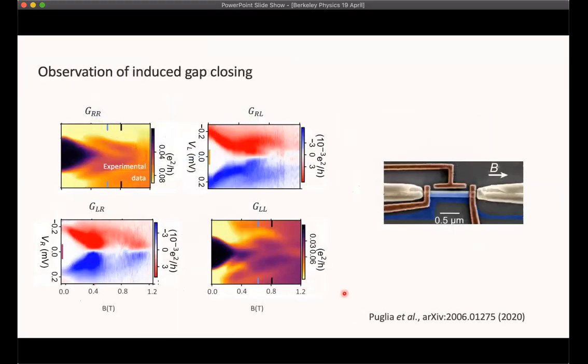All of this has been simulated data so far, so let me show you some experimental data from some of my colleagues in Denmark, where they measured these conductance matrices and observed that as the gap is shown to close locally, so is the gap shown to close non-locally. And there are some additional considerations and demonstrations of local disorder not influencing the non-local conductance measurements that you may be interested in checking out.